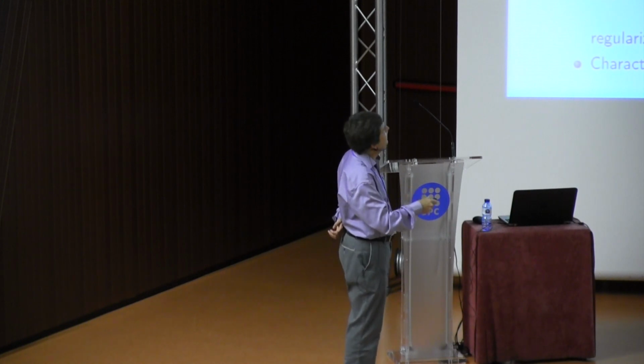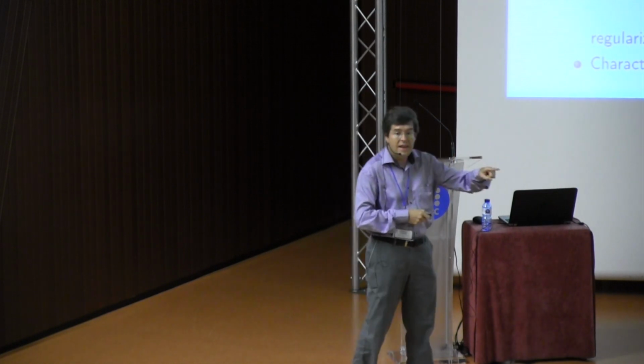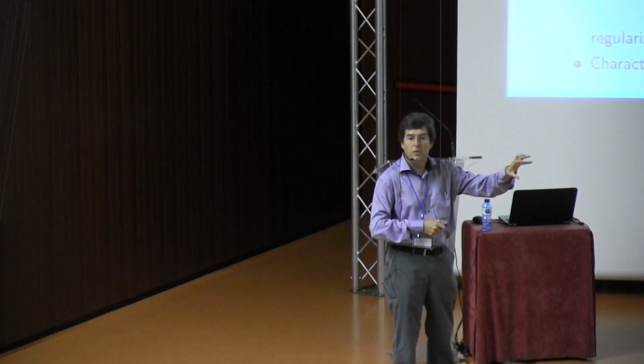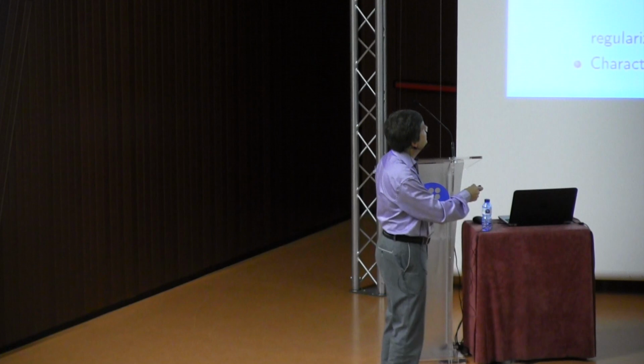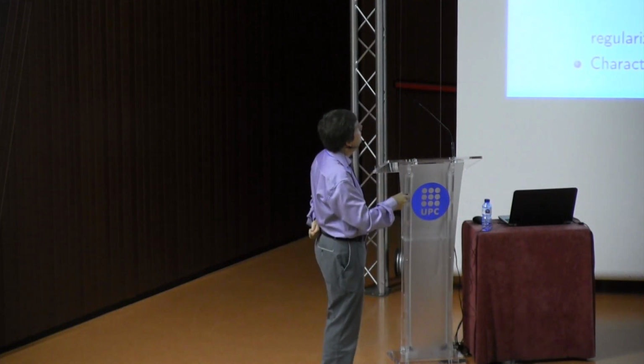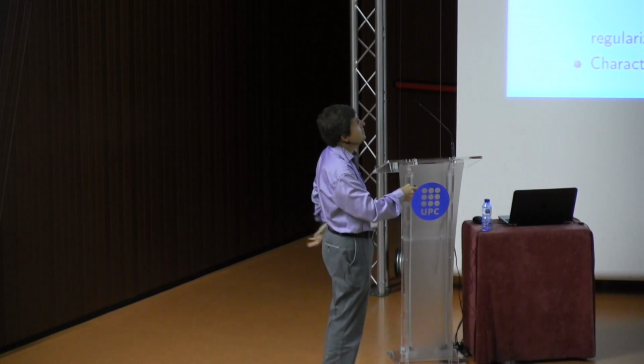I propose a very simple extension of the classical model by quadratic contributions, quadratic in the gradient, and quadratic with respect to the difference between the plastic strain and the microplastic strain. This is the place where I give some meaning to this higher order degree of freedom. The microplastic strain is linked to the plastic strain itself. This modulus here is a higher order modulus, can be interpreted as a penalty term which penalizes this difference.